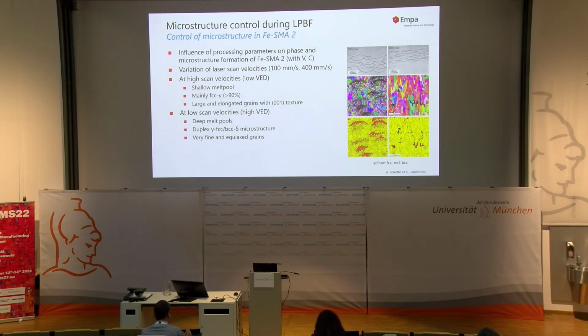So here we looked into the influence of processing parameters on phase and microstructure formation. Here we use the second alloy, but this doesn't matter at all in this case. And we varied the laser scan velocities between 100 and 400. What we can see at high scan velocity, not surprisingly, is shallow melt pools, mainly FCC, 90%, and large and elongated grains with 001 texture. At low scan velocities, we get much deeper melt pools. We get this duplex FCC, BCC microstructure and very fine equiaxed grains.